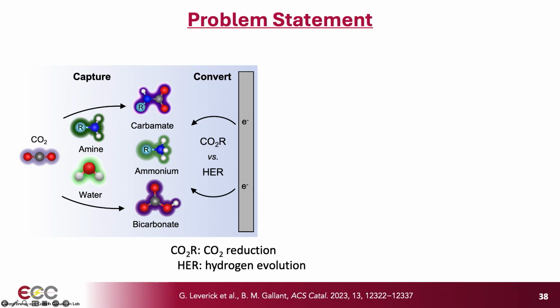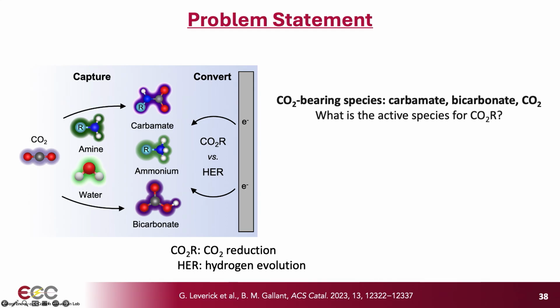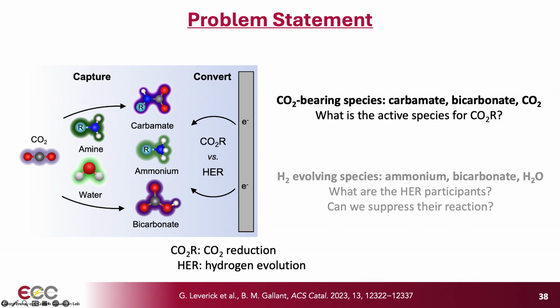And now we're trying to convert CO2, captured CO2, to a product in a system that has 3 possible CO2 participants. So there's carbamate, that's the CO2 bound to the amine. There's bicarbonate, and there's physically dissolved CO2. And we also have 3 possible hydrogen evolution reaction participants. There's the ammonium cation, there's water, and there's bicarbonate. So we need to find a way to systematically figure out which species are responsible for certain reaction pathways, and then we can design to select the ones we want.